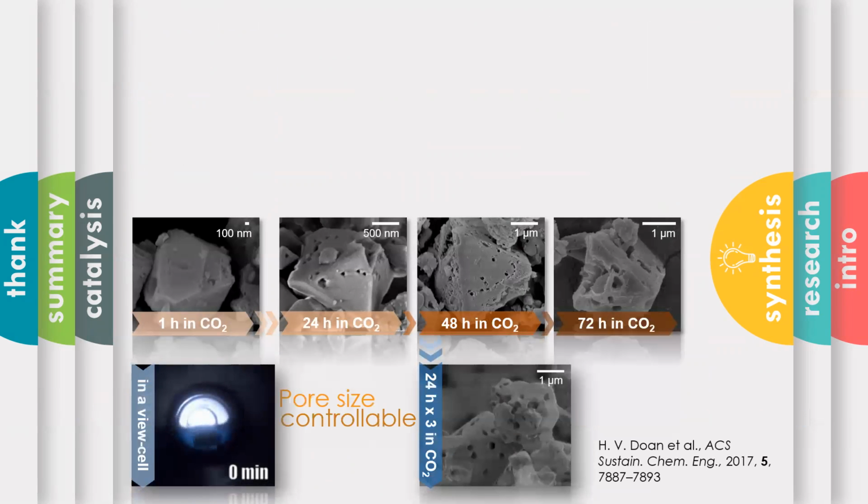Our results show that MOF properties can be adjusted by changing CO2 pressure and reaction time, and the number of macropores increases with longer exposure to CO2. A finely divided network with interconnectivity was observed in the sample synthesized in CO2 over 24 hours.